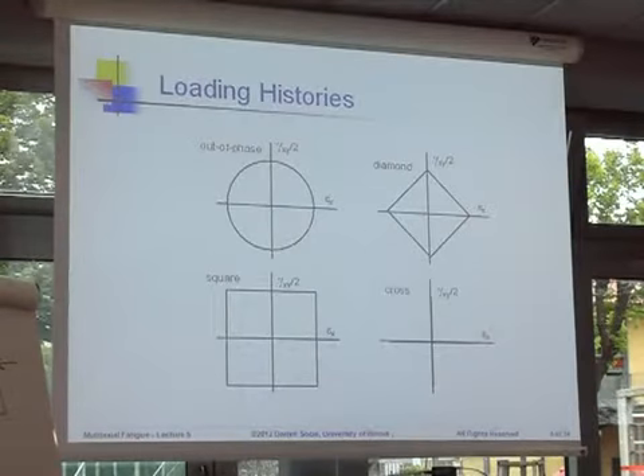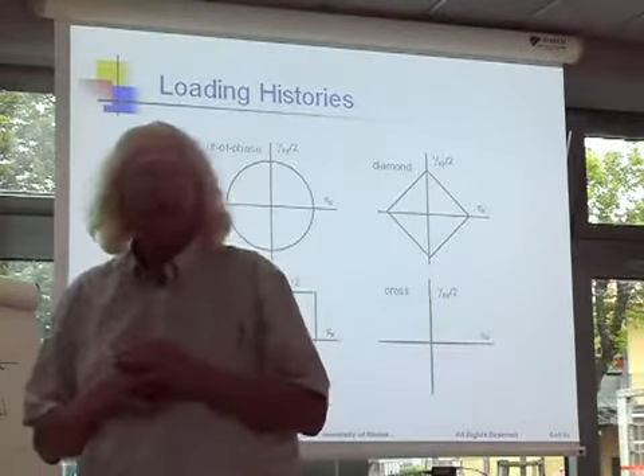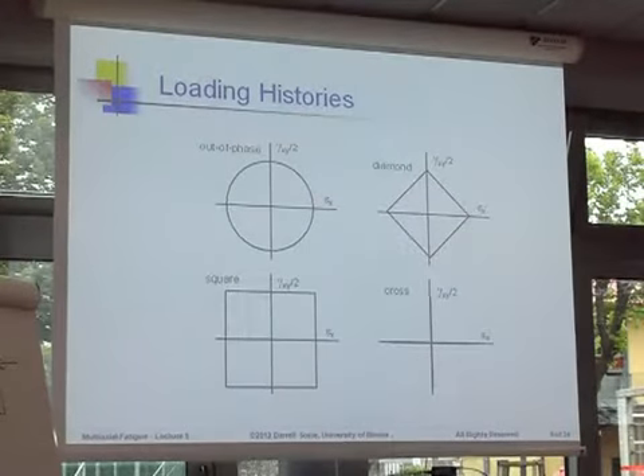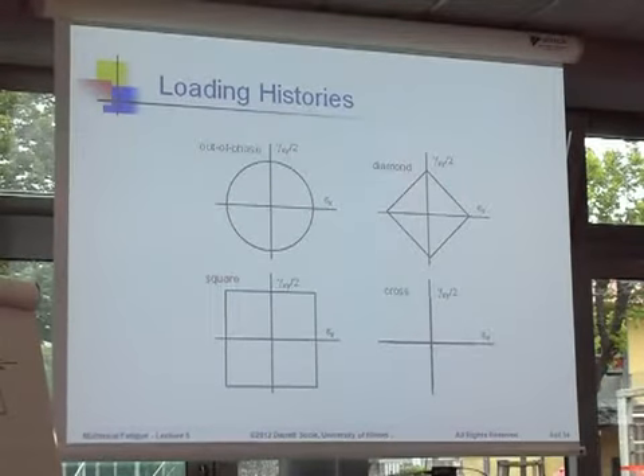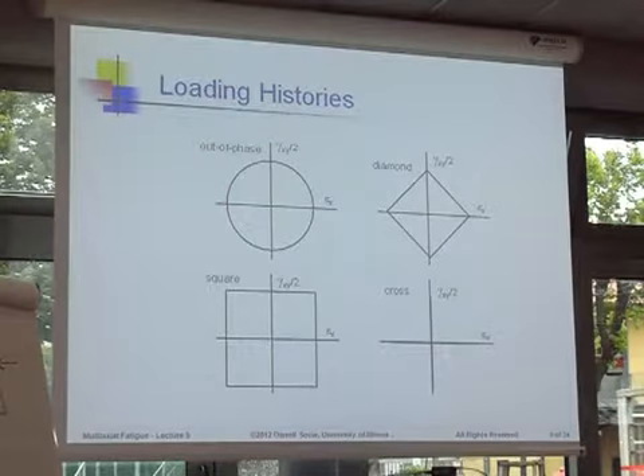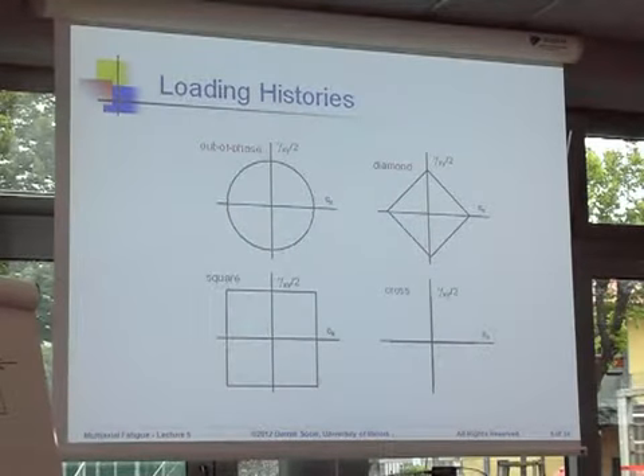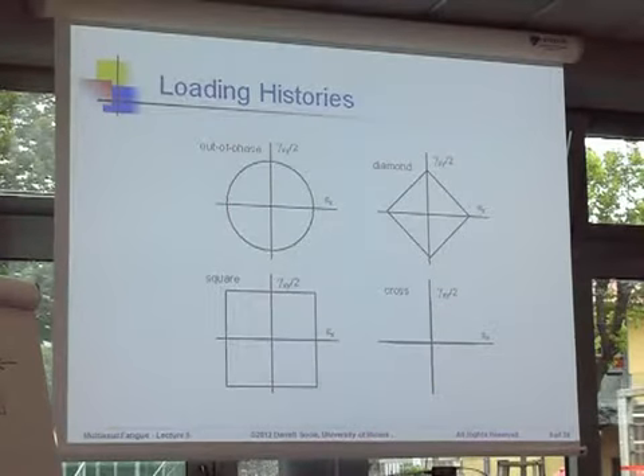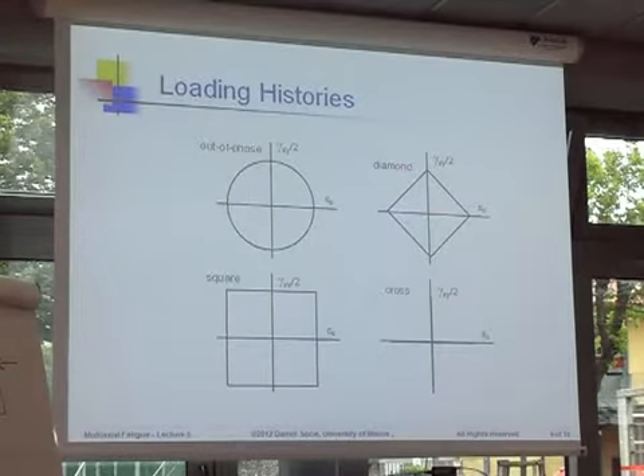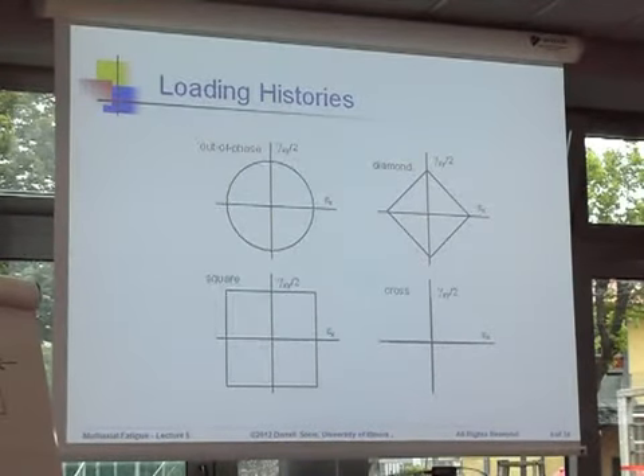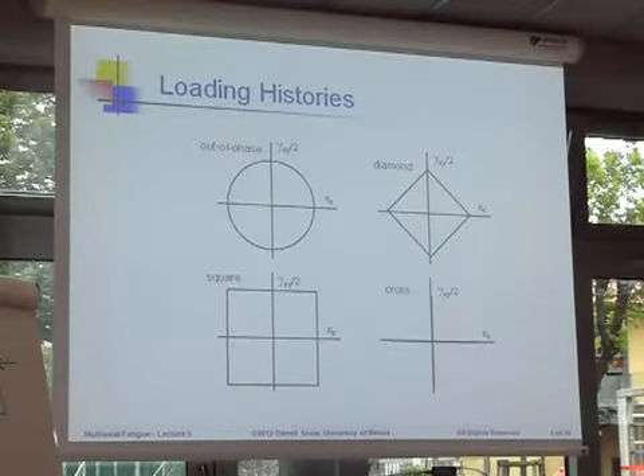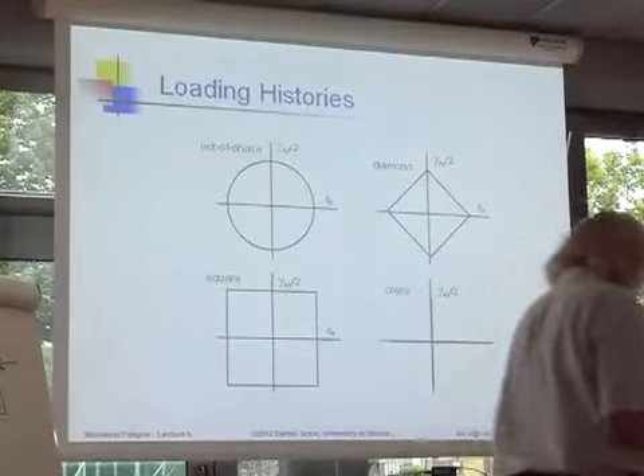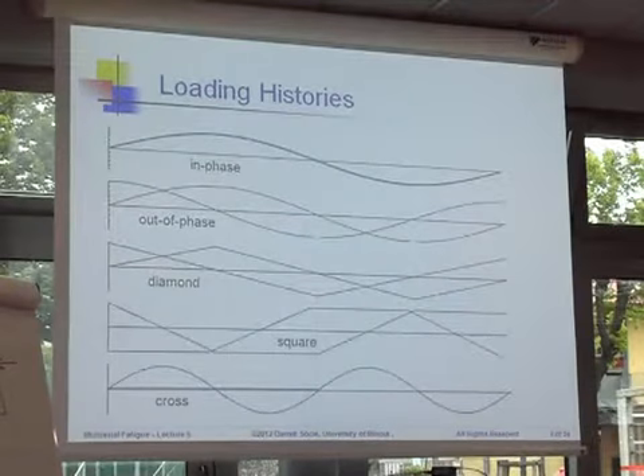So I'm back to my quiz experiments. Can we understand these concepts of out-of-phase loading? I want to make up 5 different loading paths. The first loading path is an in-phase loading path just for comparison. The second loading path is an out-of-phase loading path of sine waves. The third loading path is an out-of-phase loading path of triangle waves, and so you get a diamond instead of a circle. Then you can have a square path, and then I can have a different kind of out-of-phase loading, one cycle of tension followed by one cycle of torsion. And if you want to see these loading histories, that's what they look like.